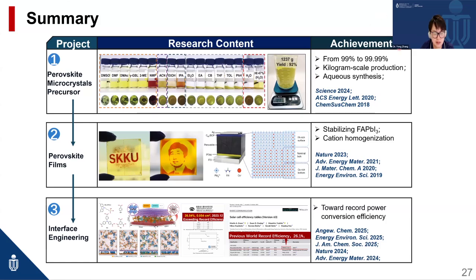And we got high quality perovskite microcrystal precursors synthesized from 99% raw materials to 99.99% perovskite precursors using an aqueous synthesis method. We also fabricated high quality perovskite film by cation homogenization and interfacial engineering to make the perovskite efficiency higher.